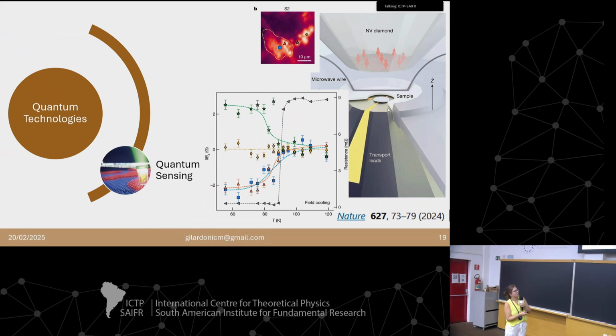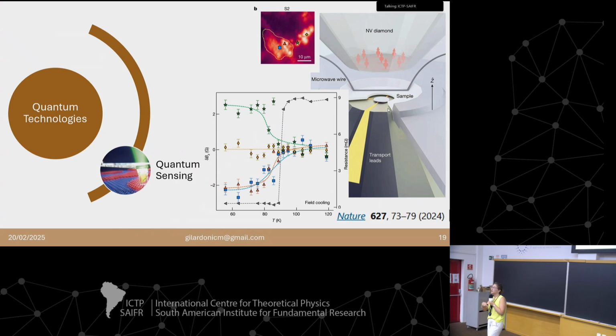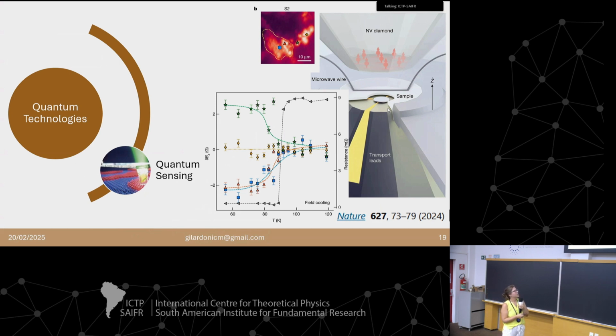At some point, I did a journal club when this was still on arXiv. They're looking at individual NVs within the anvil cell, and they're correlating the magnetic field that these NVs are seeing to the superconducting transition of this material, right? Through that, because of the Meissner effect, you can see that these NVs experience a decreasingly large magnetic field once you reach the superconducting transition.